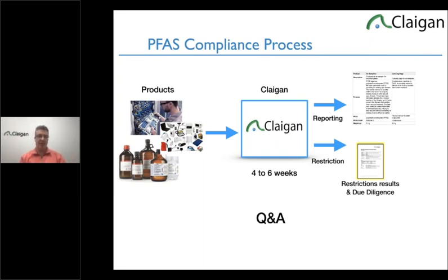But we only test the specific material. We can easily detect materials that are the exact same, so we only have to do one of them. And they're very refined on what we test for PFOA. It has to be basically a fluoropolymer or fluoropolymer coating, and then we can test by LC-MS-MS down to 25 parts per billion.